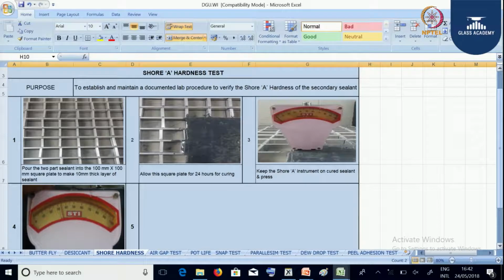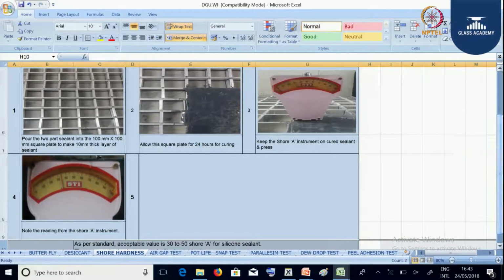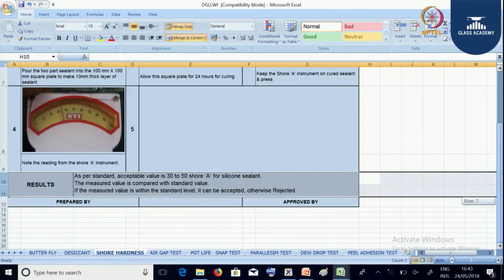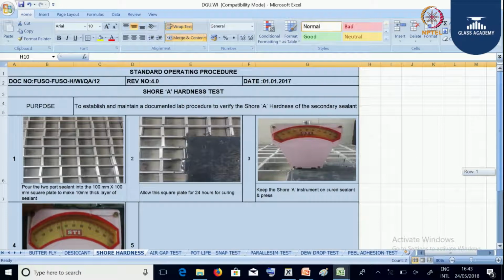You can see in figure 3, we are keeping the shore hardness tester on the sealant and trying to measure the reading. If you are getting more than 30, it is a good sealant. As per standard, the acceptable value is 30 to 50 shore for secondary sealant. If you get below that, it still requires curing, and if you get a higher value, there are chances of the sealant becoming sticky. Secondary sealant should act as a rubber material.